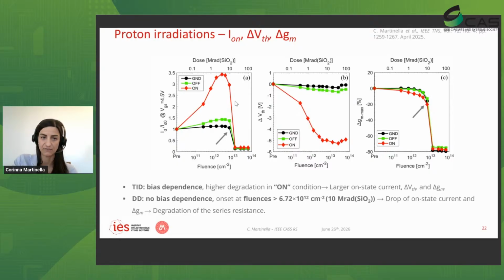And so we see that for all of them, there is a sudden drop at the same point in the on-state current and in the transconductance. This point for the onset was observed at 6.7 10 to the 12 protons per centimeter square, which corresponded to about 10 megarad in SiO2. And so what is happening here is that you are degrading the series resistance of the device.